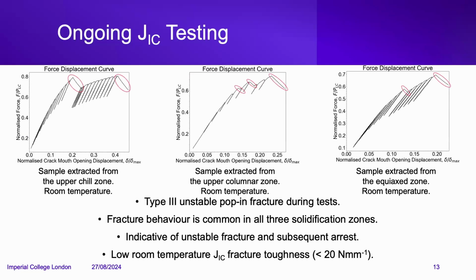And so far, some room temperature tests here show type 3 unstable pop-in fracture. This is actually relatively common. There has been some work done on electrical steel, and this behavior does show up there. But I attribute it to an unstable fracture being arrested by a grain boundary, but more tests need to be done to actually make that a definite mechanism.